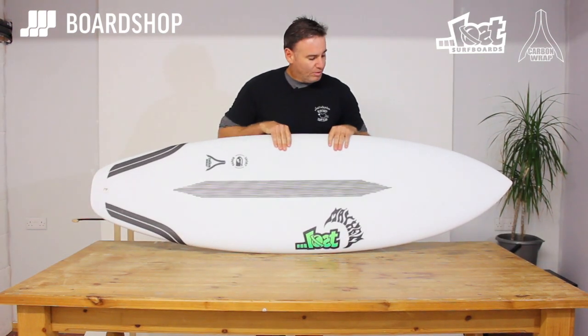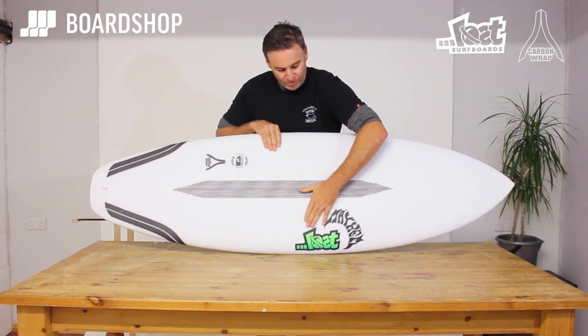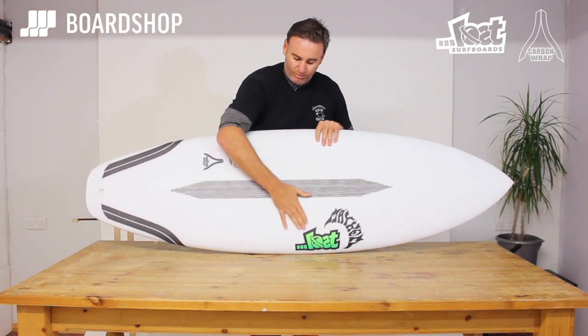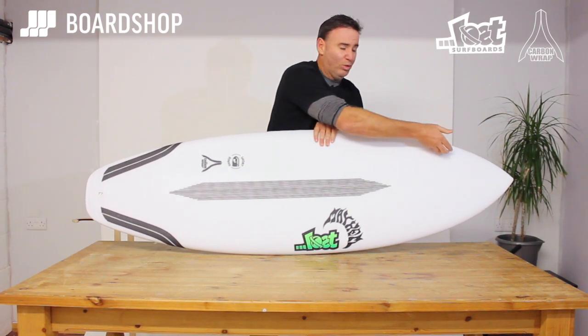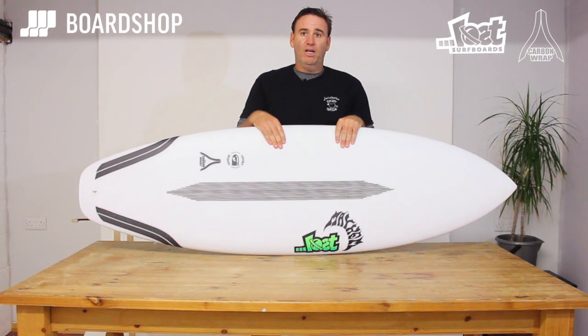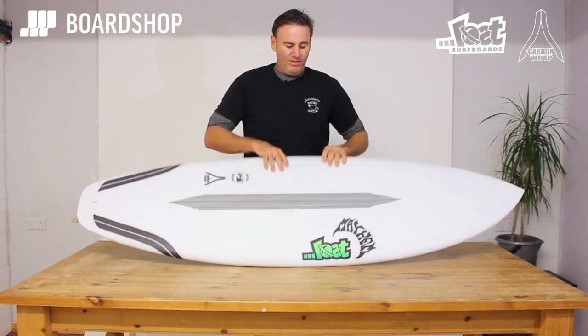The deck has one full layer of X-glass where the glass runs on a 45-degree angle. Instead of running the glass nose to tail and side to side at a 90-degree angle, all of the fiberglass on the deck runs at 45 degrees. Then there's a zero-degree twill stitch that holds the 45-degree biaxial glass together. This helps control the torsional flex on the surfboard and alleviates any stress or breaking point, which you get when the glass runs at 90 and zero degrees.